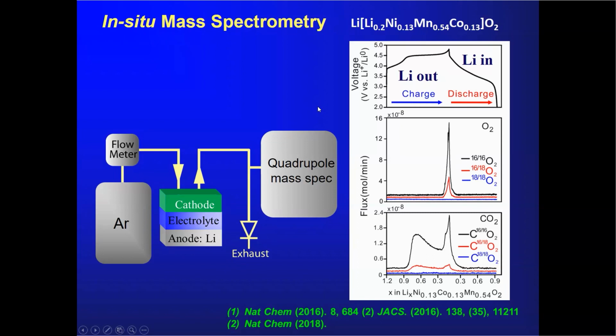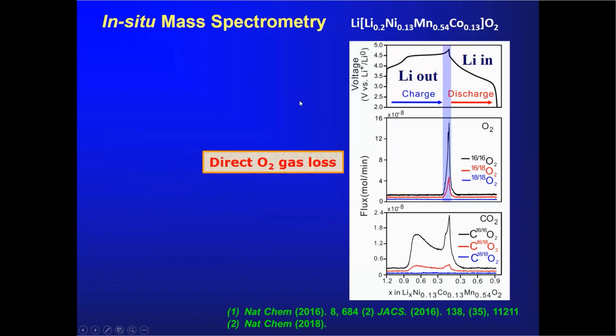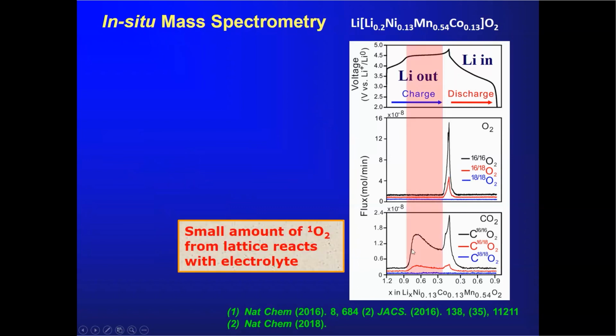And I should say that we're using a material here which is oxygen 18 labeled, so that we know that any of the species that we find are associated with the oxygen that has come from the lattice, from the material, and not simply from decomposition of the organic-based electrolyte at these sorts of potentials. And so if we look at, first of all, the results for molecular oxygen, one sees some molecular oxygen with O18 evolved here. We see CO2 evolved across the plateau with, again, oxygen 18.